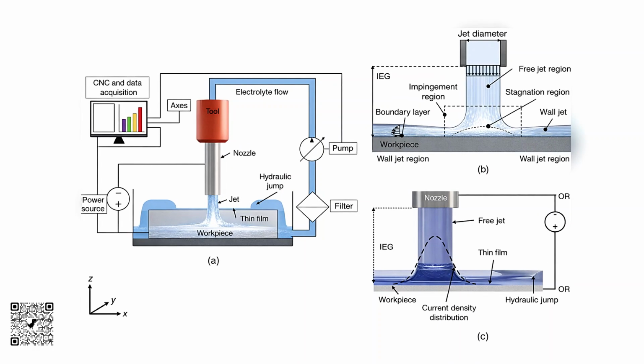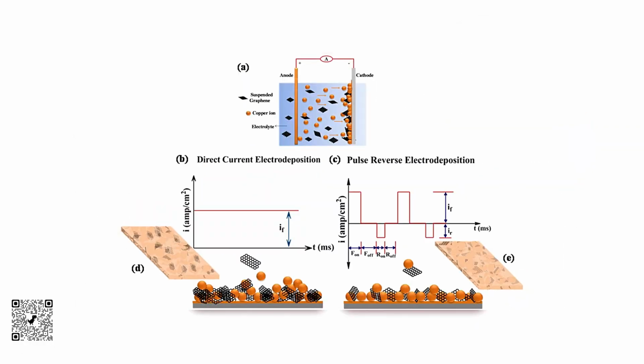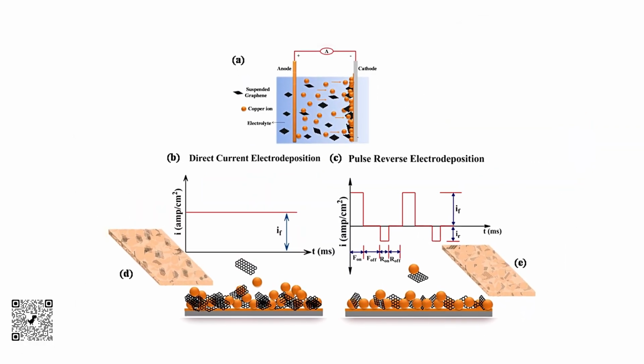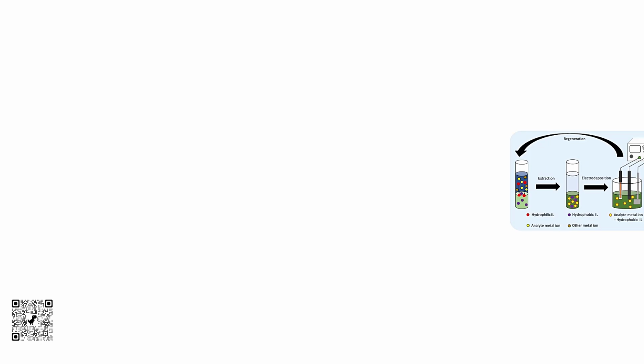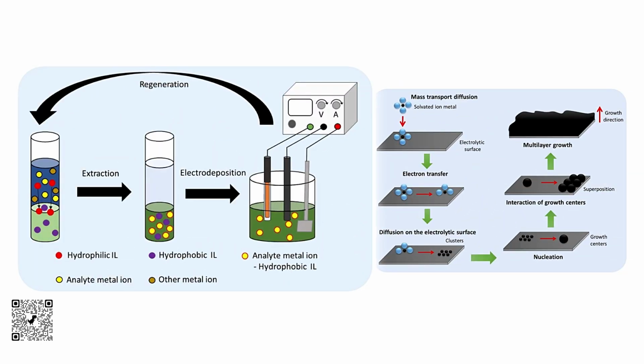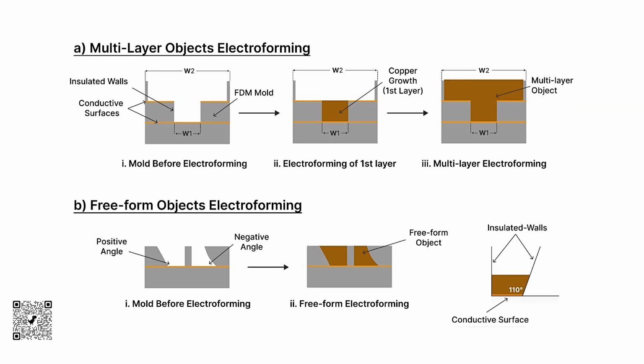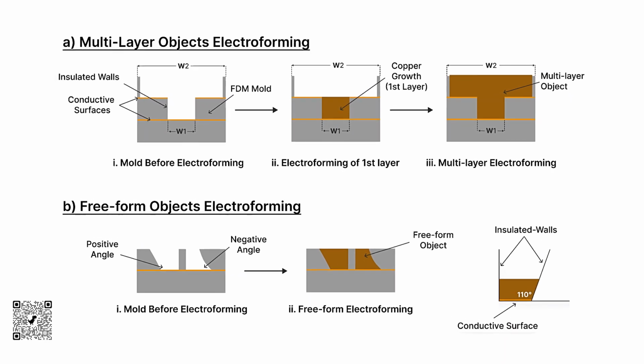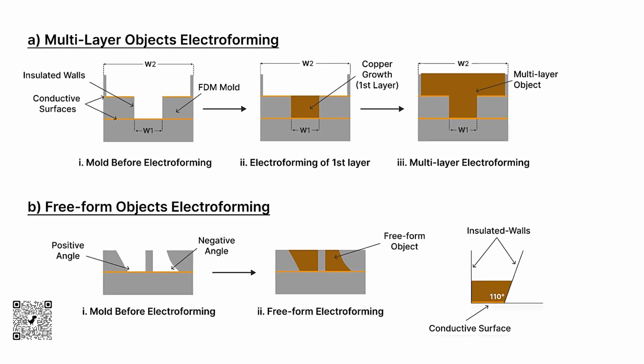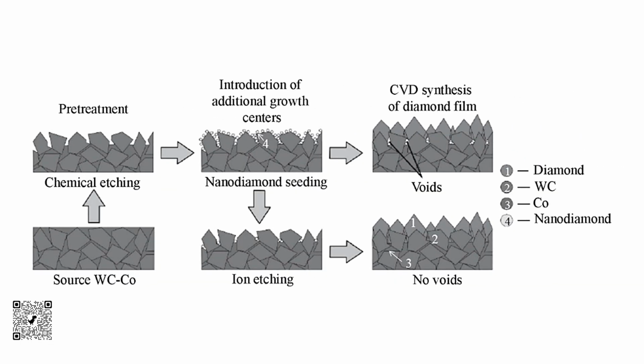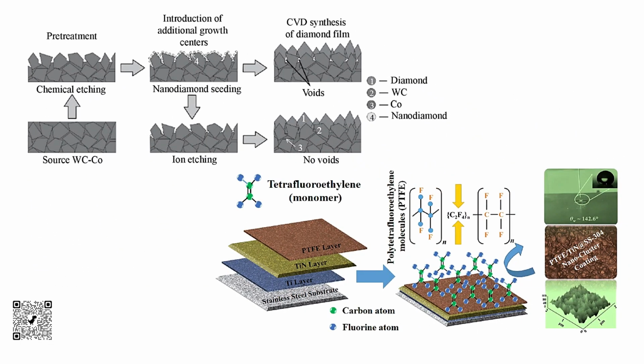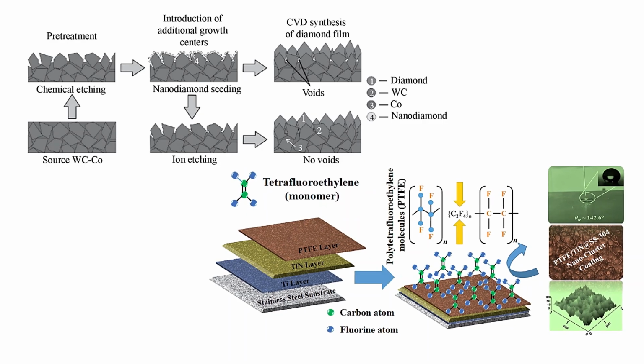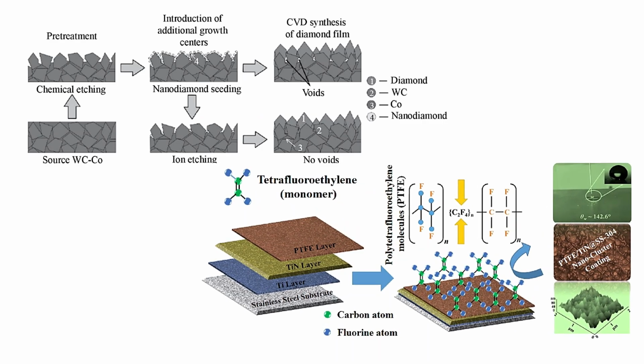Research now pushes ultra-high-speed jet plating, pulse reverse waveforms that create nano-twinned copper, ionic liquid baths that finally plate aluminum and titanium, and hybrid 3D print electroform methods that turn plastic lattices into solid metal. Composite coatings embed diamond or PTFE for wear or low-friction surfaces. Trivalent chromium replaces toxic hexavalent chrome, and AI-controlled baths slash waste.